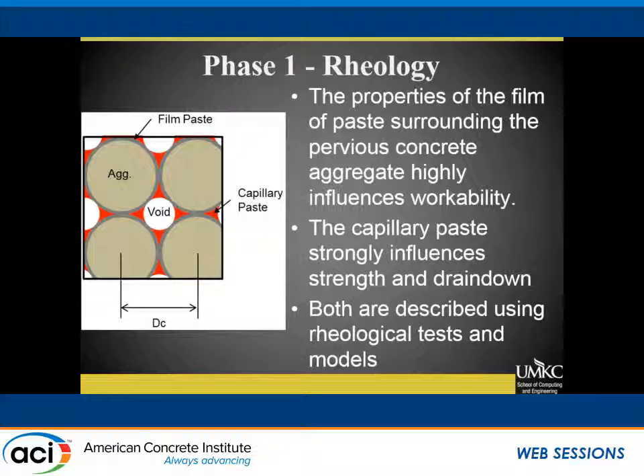The kicker is if our paste is too mobile, then we can't get it to sufficiently surround that aggregate or fill in those voids and create a meniscus. If it's too fluid, then it drains to the bottom, and that's not good. It could plug our base up, but in essence, we have no strength at the top, and we're in trouble. So, looking at this, we say, all right, how can we characterize this behavior? And we use the concentric cylinder rheometer.